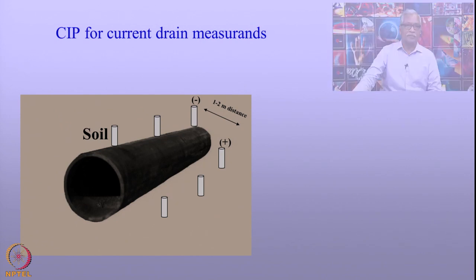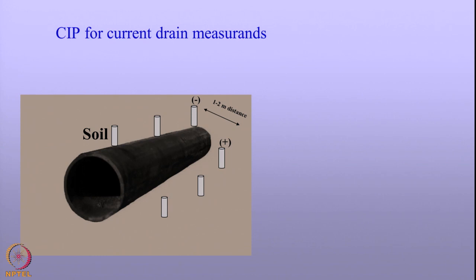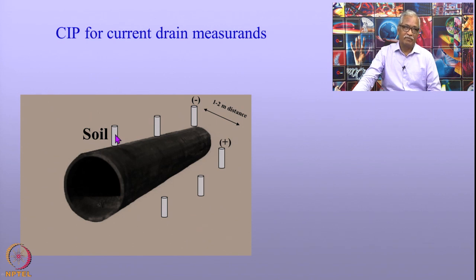There is another kind of information one seeks from the pipe to soil potential measurements. This again is close interval potential measurements. The difference is that one electrode is kept well above the pipeline, the other on either side of the pipeline at a distance of 1 to 2 meters. The potential is measured between these two reference electrodes, and if this potential is positive, the current enters in one direction. If it is negative, the current enters in the other direction. So, the advantage of this technique is you will come to know whether the pipeline is receiving current or the pipeline also acts as a drain wherein corrosion occurs.